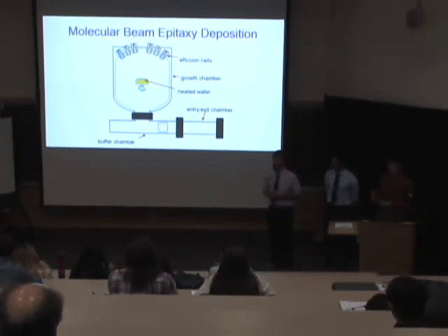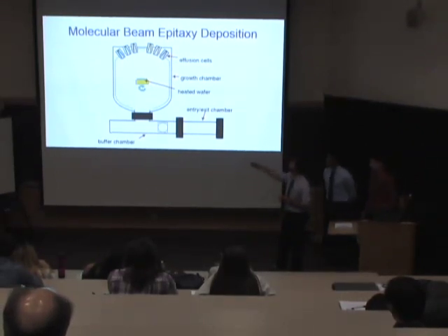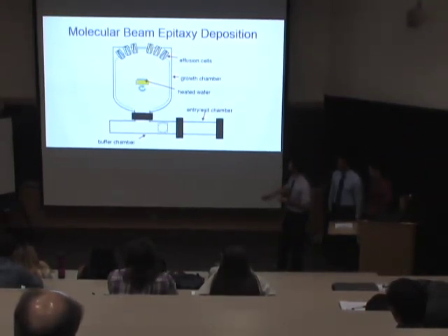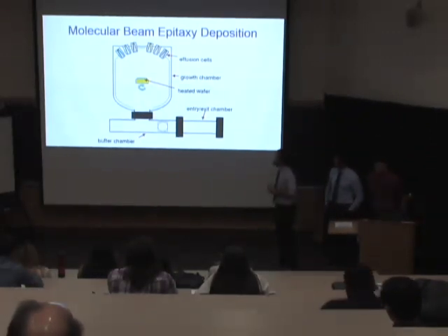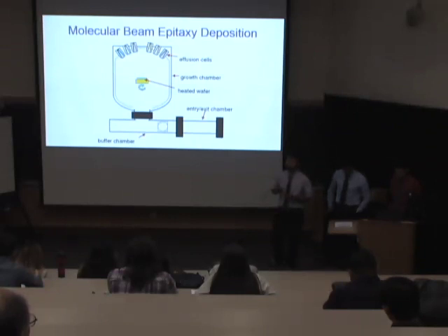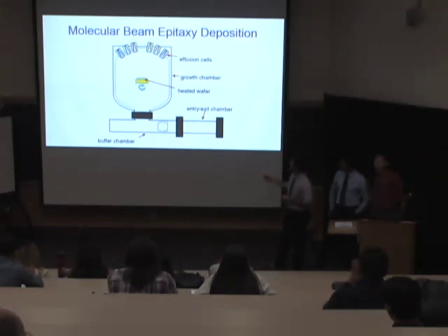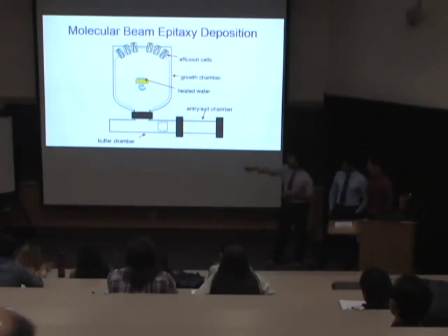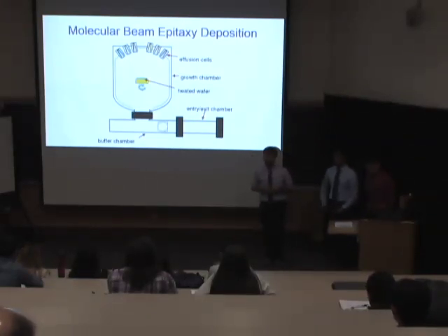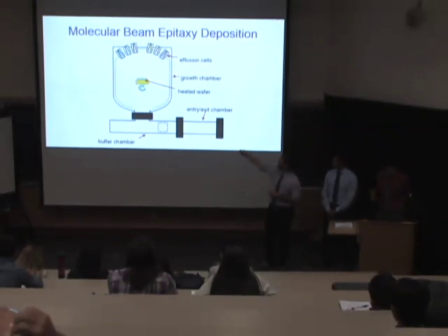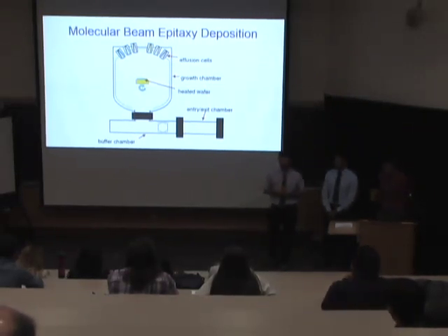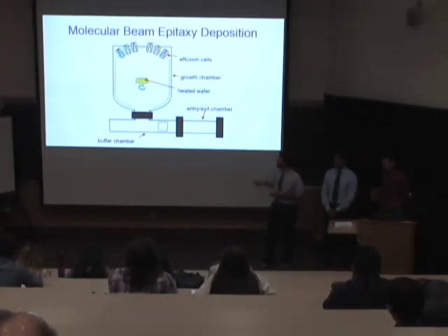Growing is a term that we use for deposition, or laying the atoms on top of our substrate. So we see right here, this is the entry chamber. We load our substrate, which is a flat surface, usually given so that we can grow materials on them. It enters here, and once this chamber has the same pressure as the rest of the system, we can then move our substrate into the buffer chamber. From here, we can then put it into the main chamber. And as you see, we heat our wafer to whatever temperature it is before we deposit. Each one of these effusion cells holds possibly a different type of material that can then be vaporized and shot right on top of our substrate. And that is how we grow it.